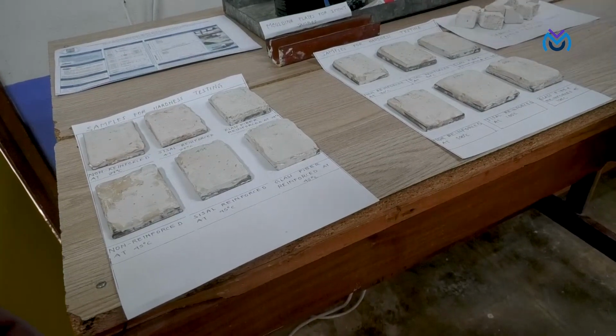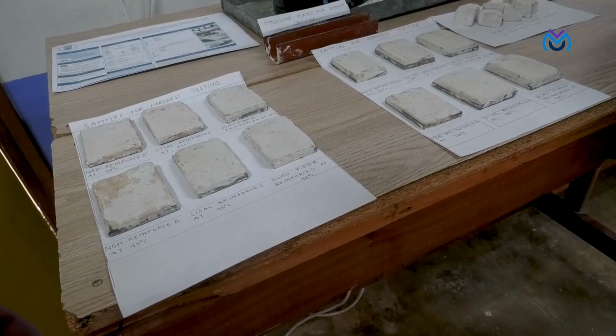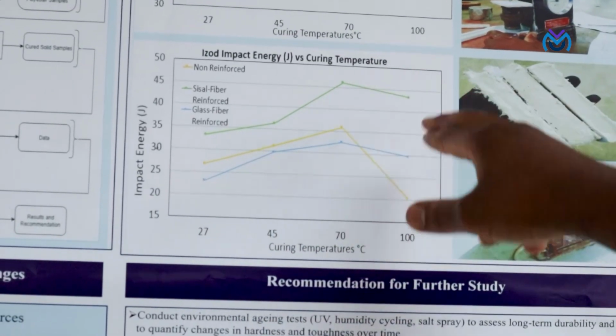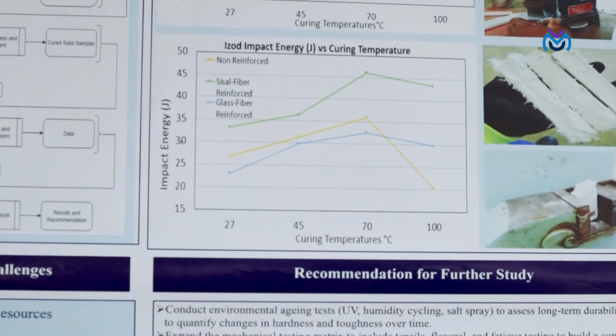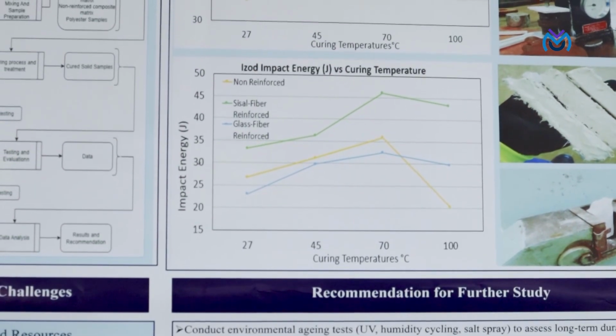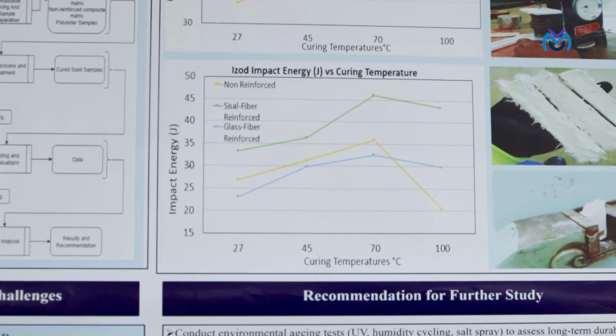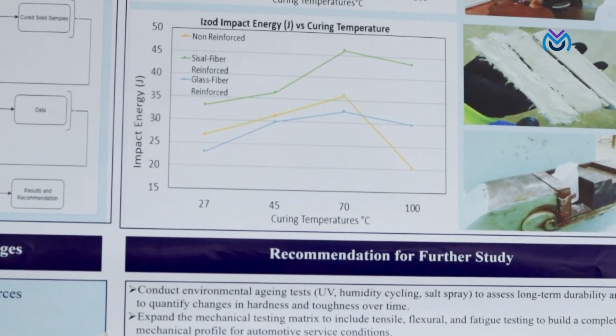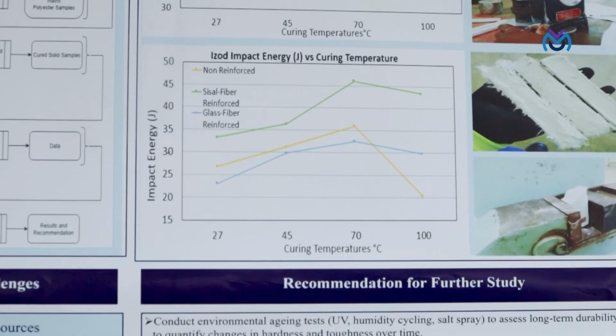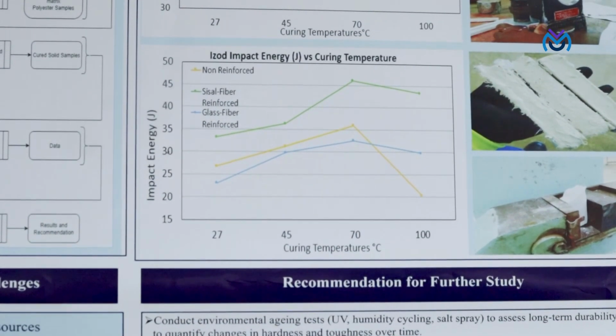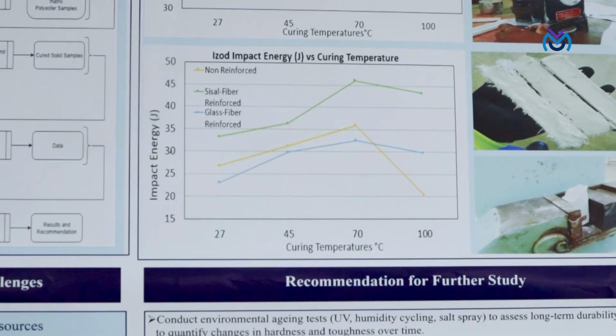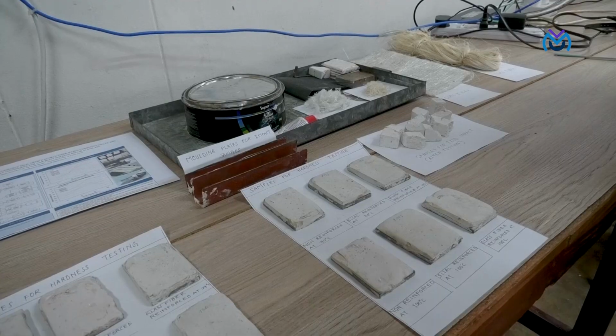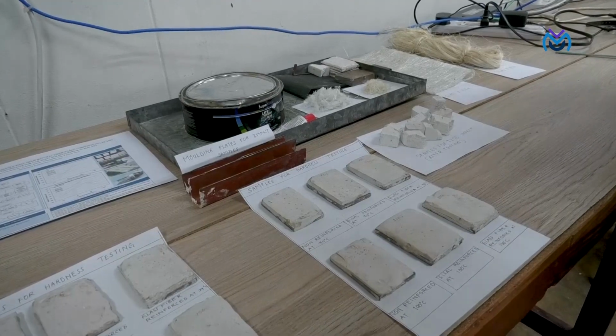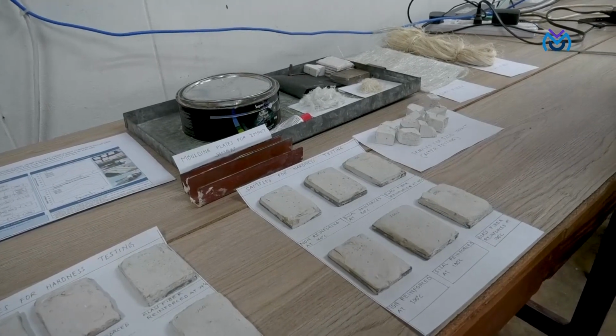Under impact testing, we also have the sisal fiber performing the best. This was to measure the toughness of the sisal fiber. And the non-reinforced was also performing competitively, but because of overheating at above 70, the microstructure degraded. So without reinforcement, it shows that the polyester resin degrades above 70 degrees Celsius.